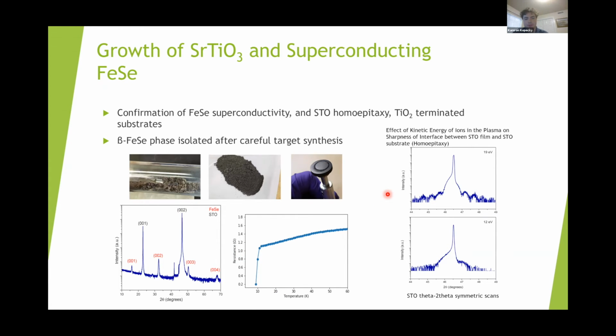And then from there, once we've shown that we have epitaxial superconducting iron selenide, we set out to prove the homoepitaxial growth of strontium titanate, in which strontium titanate was grown with varying peak kinetic energy distributions for the ions in the plasma. From these peak kinetic energies, we can determine the sharpness of the interface and the homoepitaxial nature of the growth. And here we can see at lower peak kinetic energy distributions, we have improved homoepitaxial growth, as there are fewer reflections, indicating there's more correctly aligned strontium titanate growth.